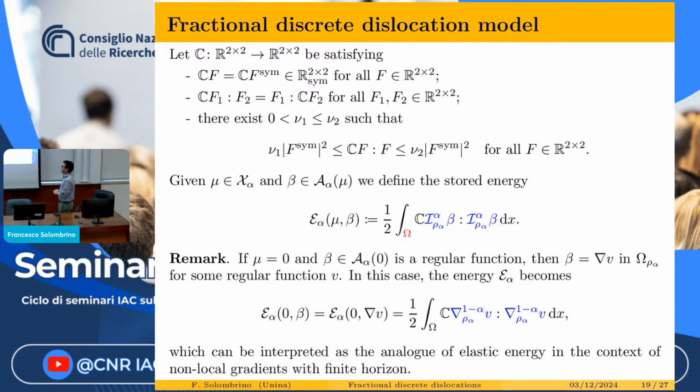Then there are the usual assumptions on the elasticity tensor, but these are the really standard ones. So the difference with what was done before is there is no core radius. Core radius is replaced by use of Riesz type transforms on the linear elastic strain. And now your constraint can be formulated as a differential one, as it must be, instead of cutting out some pieces of your material and reformulating the constraint in an integral way. And so this energy is defined on the whole of your configuration. So it has a lot of similarity. It really resembles that one, but it's formulated in a different way.